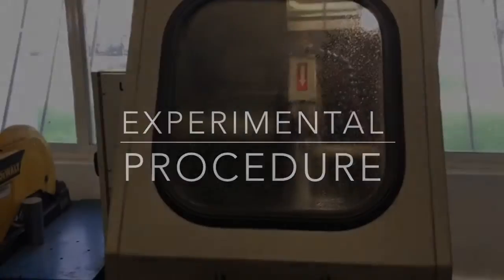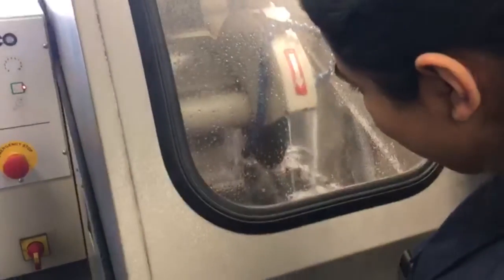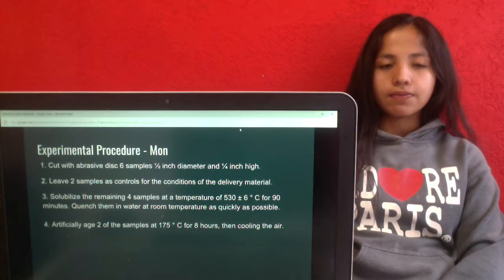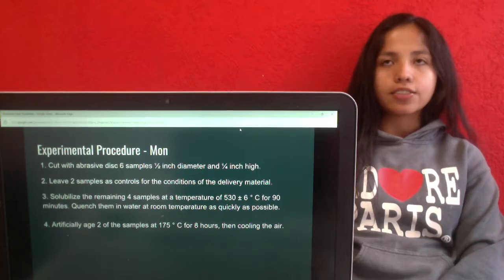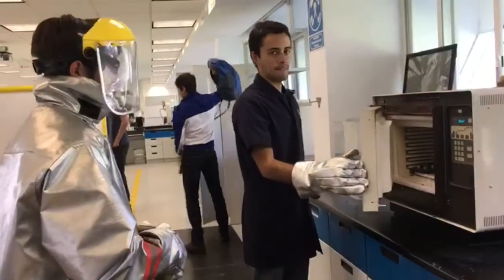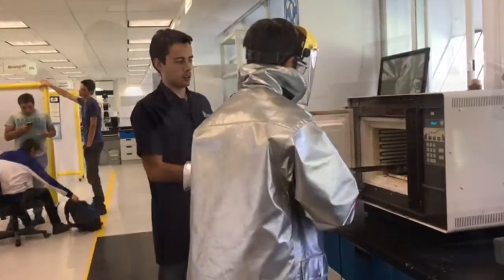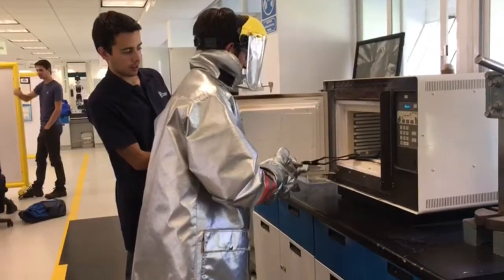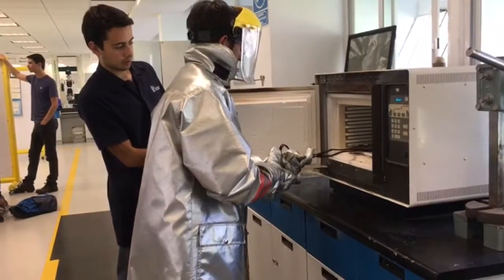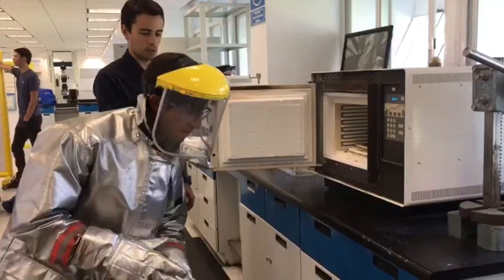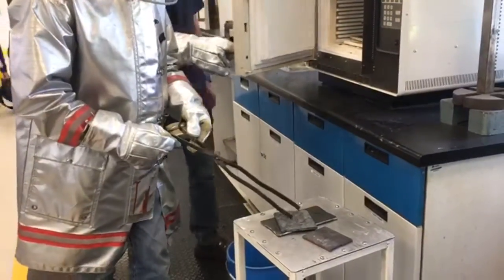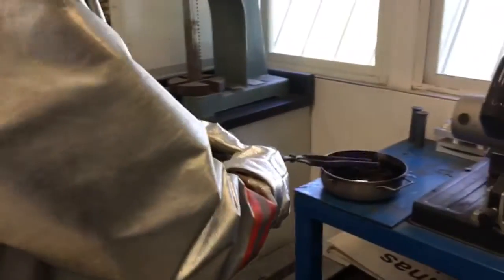The experimental procedure of this practice was first to cut 6 samples of aluminum 6061 with the abrasive disc. Then we leave 2 of the samples as control, and the 4 remaining we introduce into the muffle at 530 degrees for 90 minutes. Then we quench them in water at room temperature.